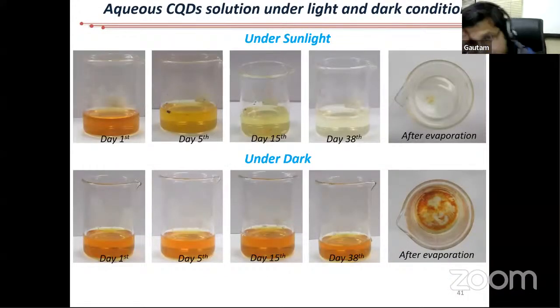And then once we realized it, actually we kept these carbon dots for a long time in sunlight. Normally these reactions are done for 3 hours, 4 hours. We just decided to keep it for a long time. And we figured out that if you keep it for 38 days, you see all the carbon dot is gone. But a similar solution, if you put it in dark, nothing happens. It all remains there.